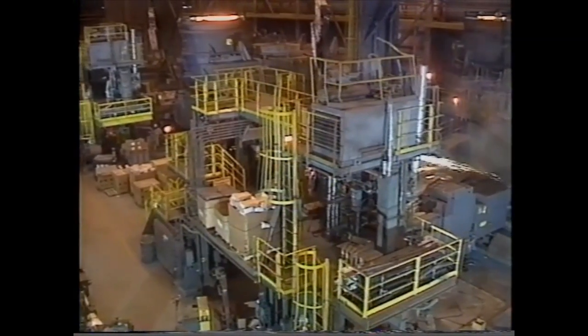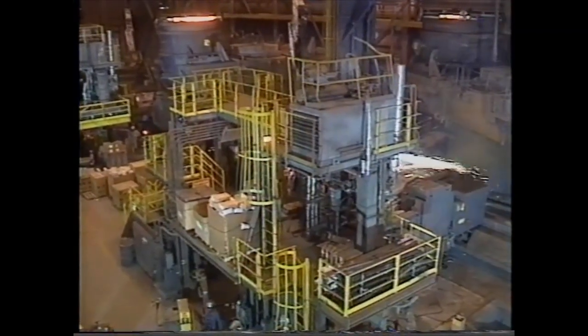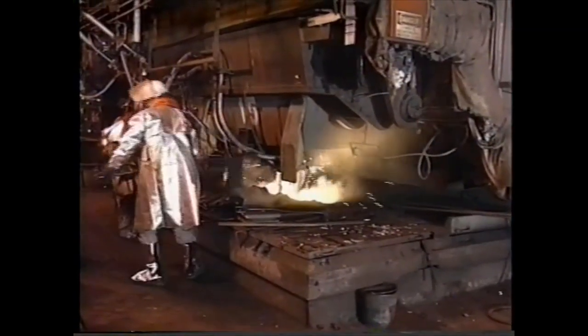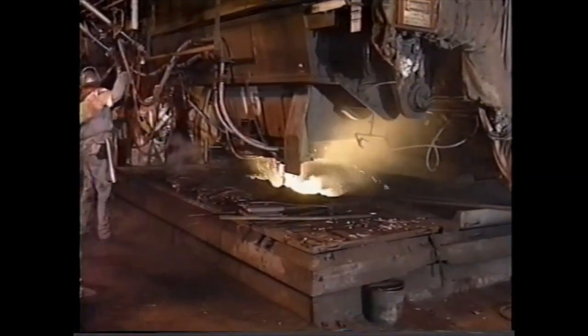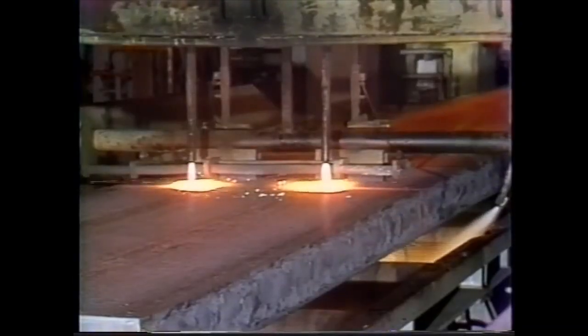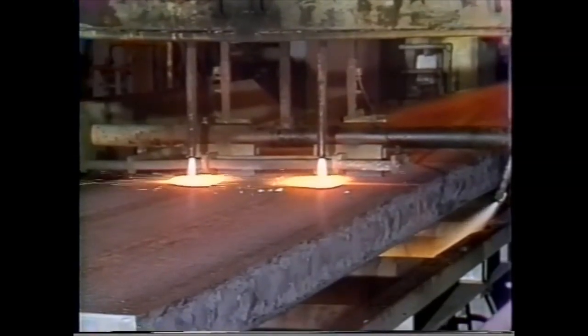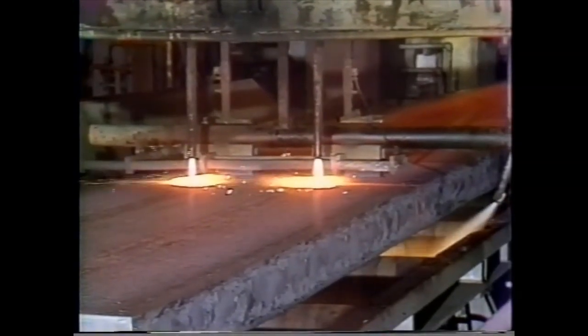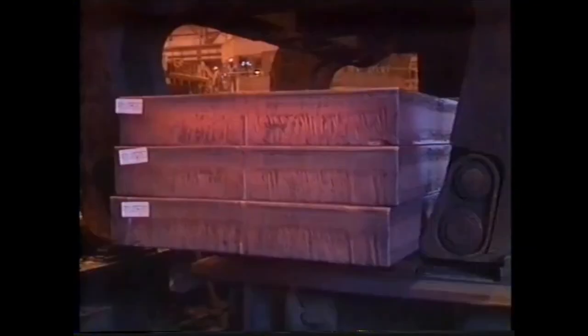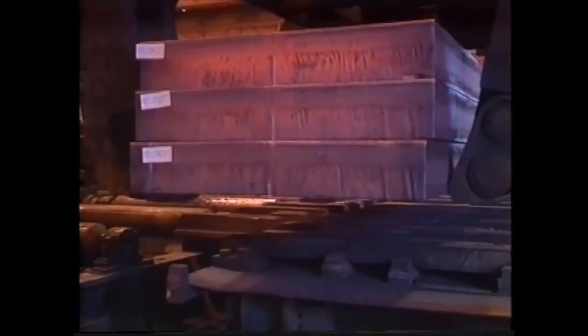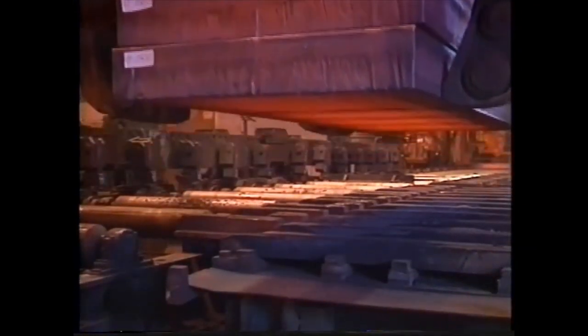Here, the liquid steel is transferred from a ladle into the top of the casting machine's water-cooled mold. As the steel passes through the mold, it begins to cool and solidify. After the solid strand exits the casting machine 52 feet below the cast floor, it's cut into slabs and transferred to the plant's plate or hot strip mills.